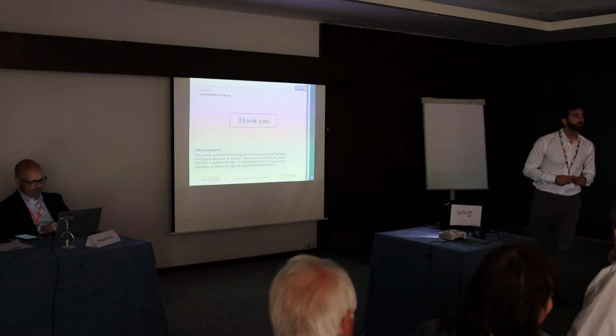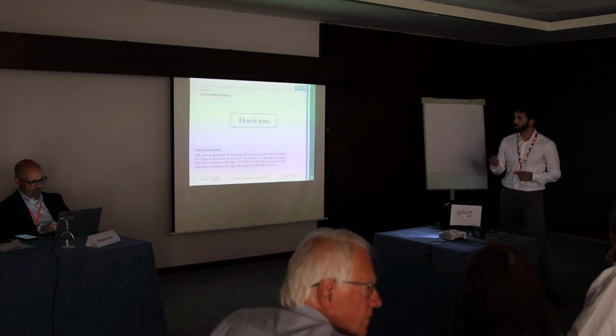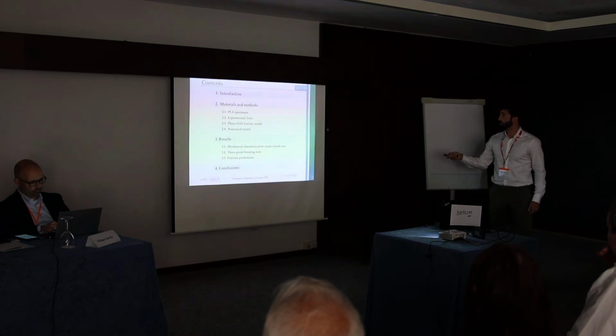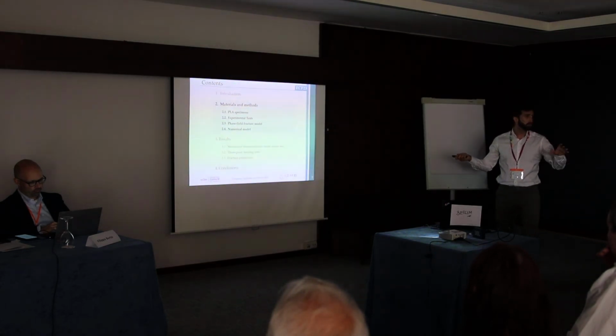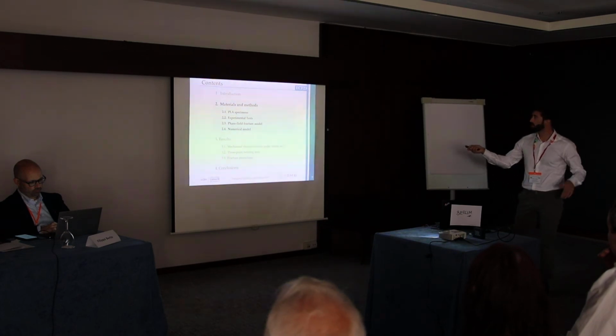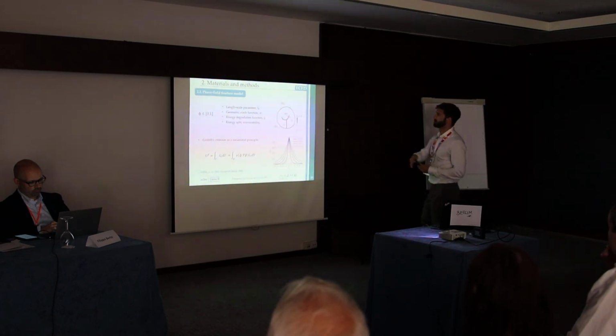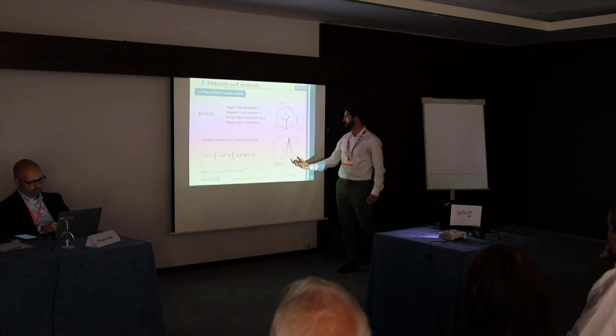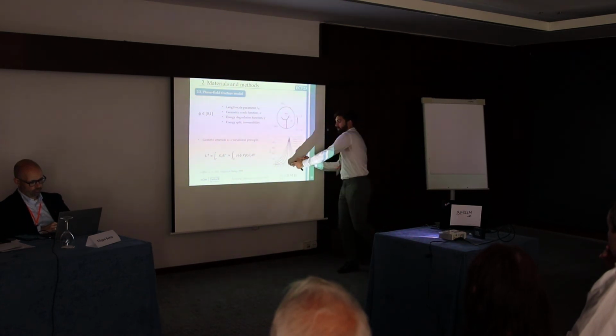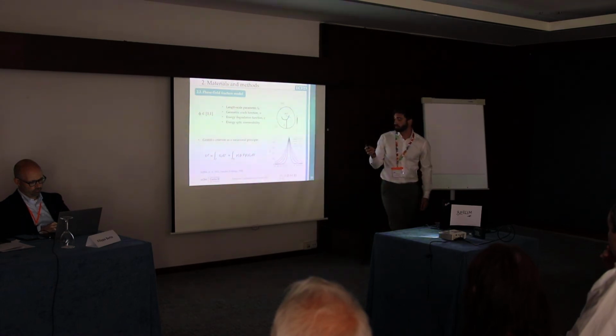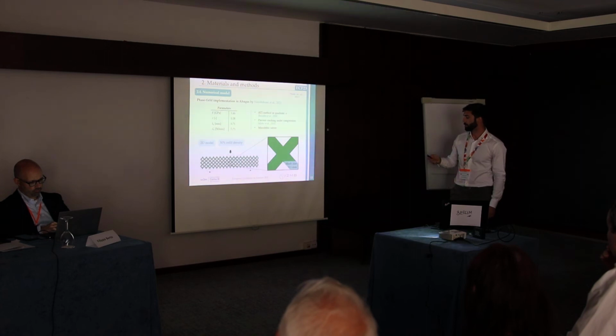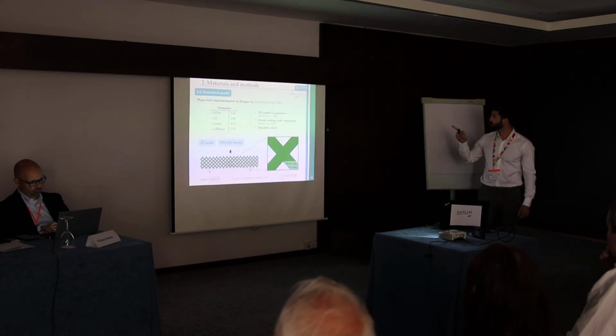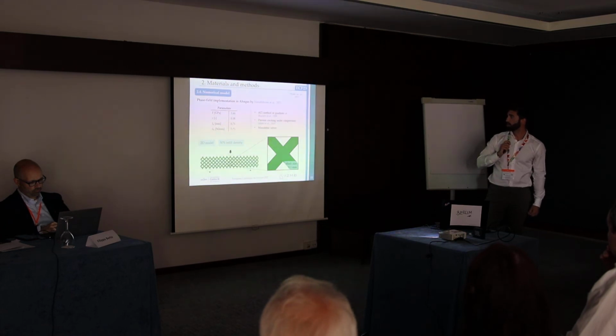Yeah. In phase field, this parameter has an important role. How did you calculate it? Well, as I said, this was a preliminary simulation just to see that the crack path is as I expected, but yes, this is very important. Maybe you know, the length scale parameter describes the width of the diffuse crack. And then we used 0.79, like in the literature. I didn't put the reference, but yeah.